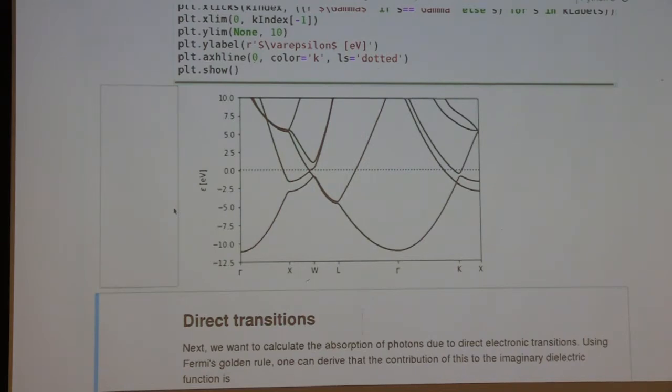Right? So this is now much more like a band structure you would see published for a given material. So this is once again for aluminum. And I'll remind you about this parabolic region here, which effectively corresponds to a free electron-like band structure. But the fact that it deviates from the parabolas, all these splits that you get here, are results of perturbations from that perfect free electron gas due to the nuclei present in the material.